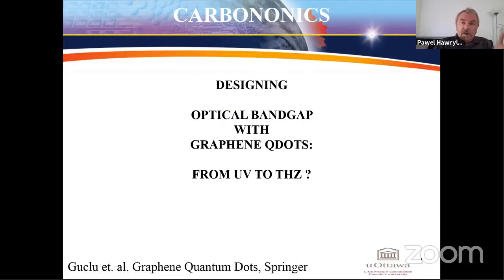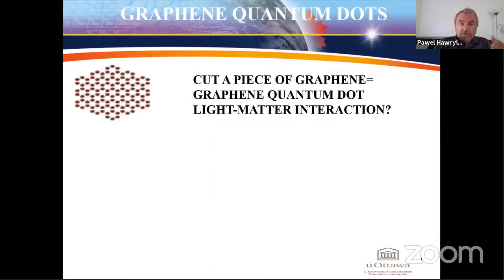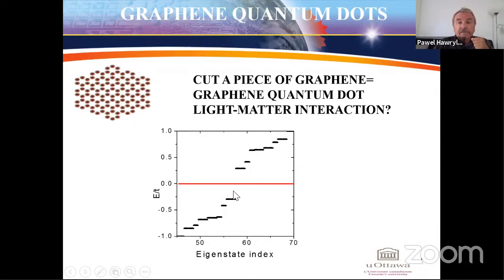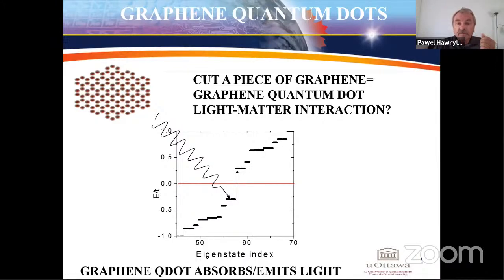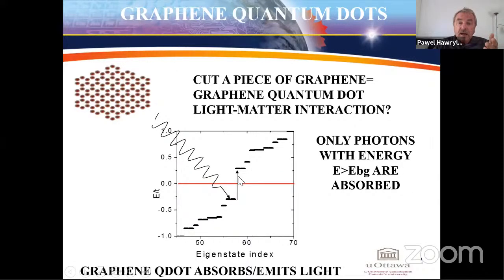Okay, so how can we design and understand an optical band gap? Well, we take a piece of graphene, we make a graphene quantum dot, and now we ask whether it interacts with light. So here are the energy levels of an electron in such a nanostructure, and there is a gap across the Fermi level, the Dirac point. Then we shine light and we ask whether there is a dipole moment that connects the occupied state in the valence band with an empty state in the conduction band. And the answer is positive. So the graphene dot absorbs and emits light. And of course, only photons with energy larger than this band gap are absorbed. So this is our semiconductor. We went from a semi-metal to a semiconductor.